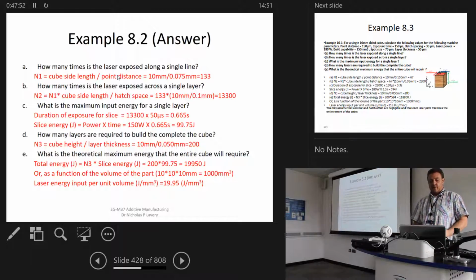That gives us the value N2, which is the value N1 for a single line times the number of lines, given by the hatch spacing in the other direction. So 133 times 10 millimeters divided by 0.1, the 100 micron hatch spacing, gives us 13,300 spots on that single layer. Each of those has a duration of 50 microseconds, so we can work out the entire duration of the exposure of the laser across the entire surface. That's 13,300, or N2, times 50 microseconds, which gives us 0.665 seconds.